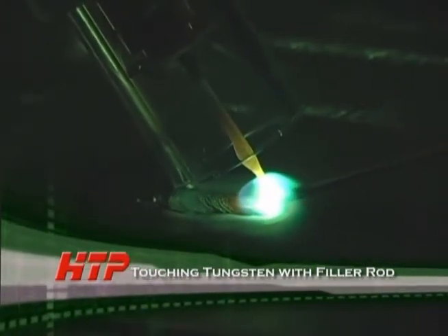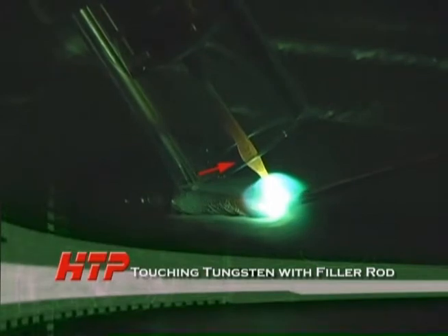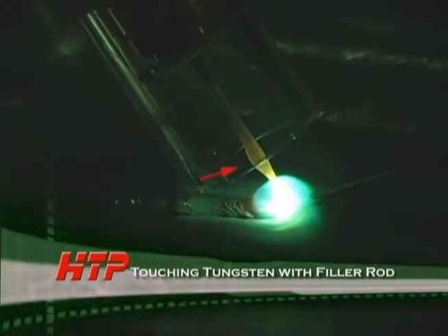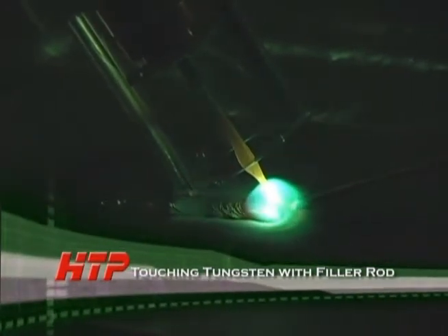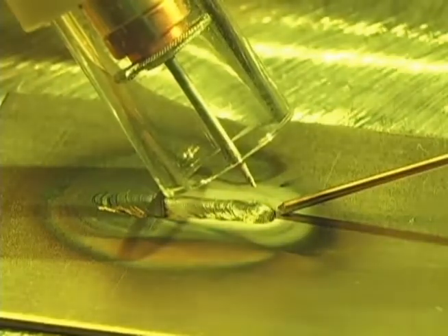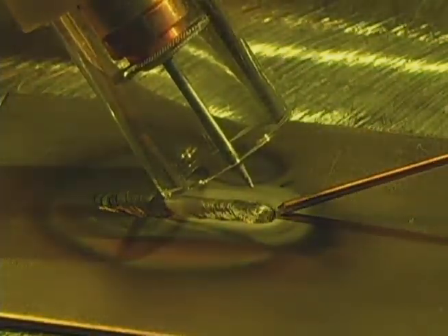By the third hit, you can see a large glob of molten steel on the tungsten, and the steel is melting off the tungsten, changing the arc and contaminating the weld. The only thing to do is to stop welding, remove the tungsten from the torch, cut the contaminated tungsten off, and resharpen it.